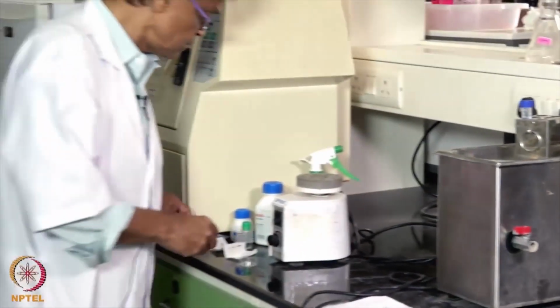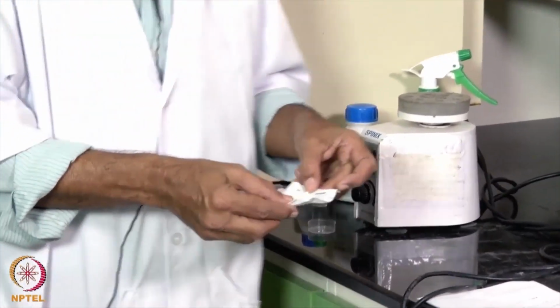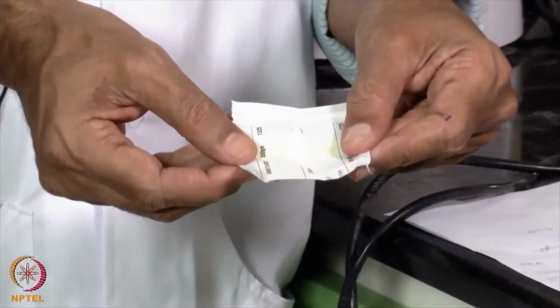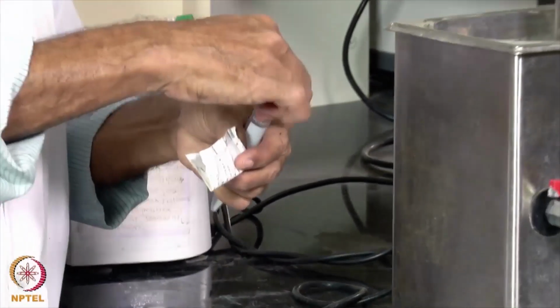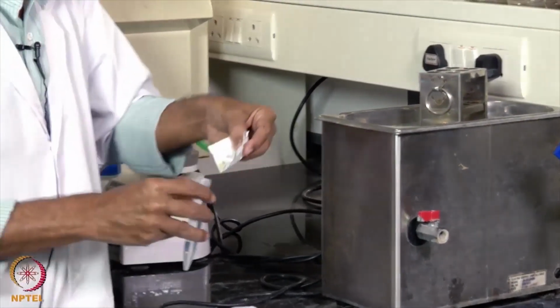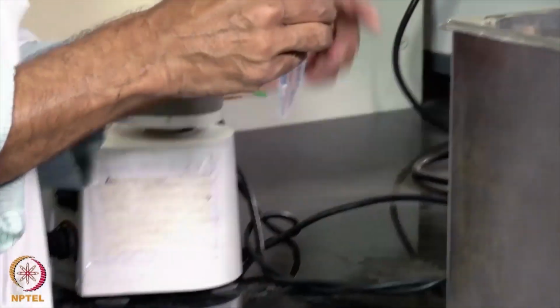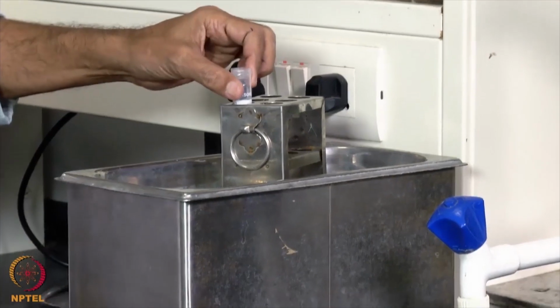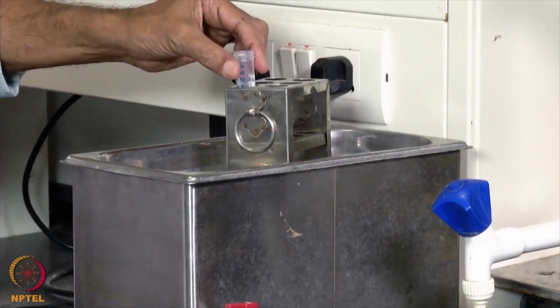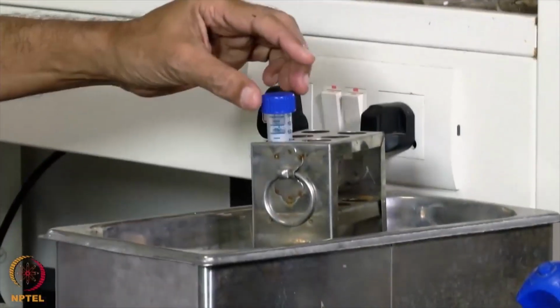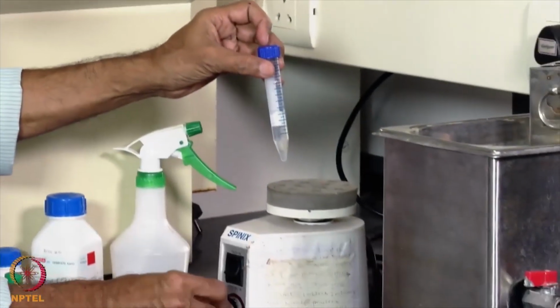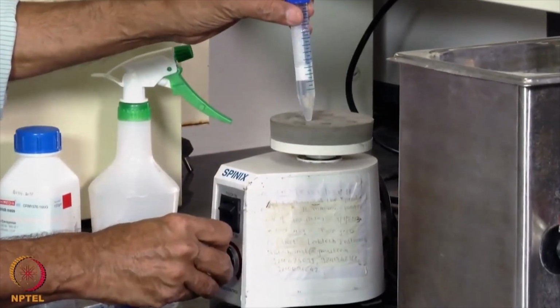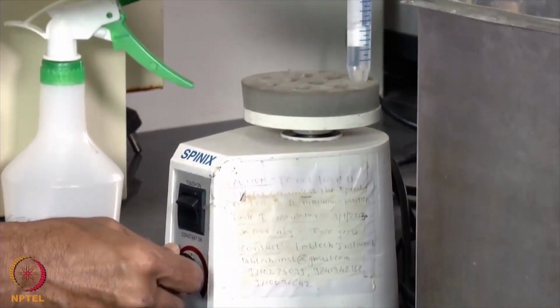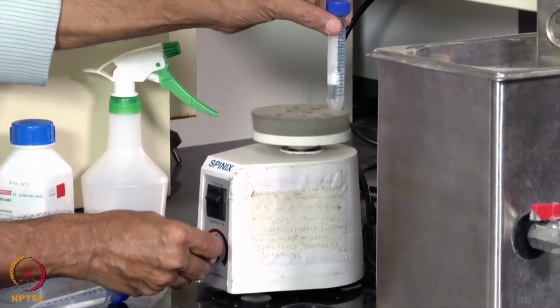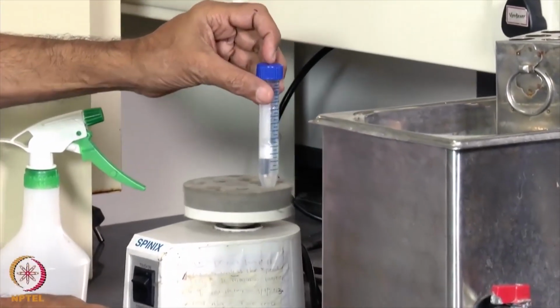We take carrageenan, 56.45 milligrams of carrageenan. We add to this hot water. Now we raise the temperature to 70 degrees centigrade for about 15 minutes, so that the carrageenan completely dissolves in it. We can intermittently mix this. This is a mixer. As you can see here, we can mix this. And then again heat it up so that it's completely dissolved.